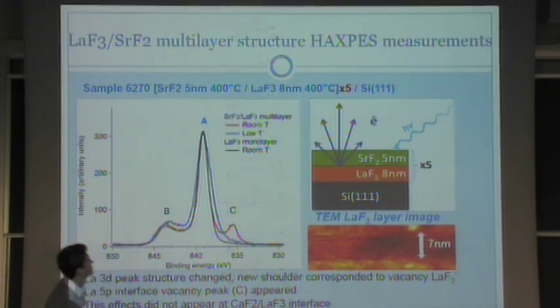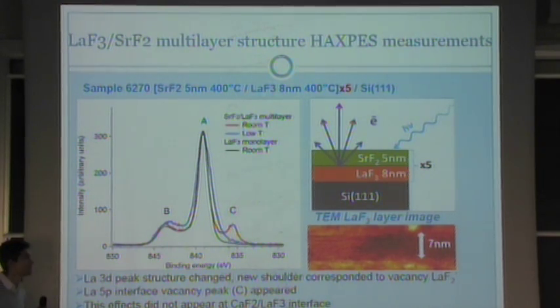Now I want to say a few words about the most interesting part of my work, which is multilayers. The multilayers were studied with the following geometry: lanthanum fluoride was under strontium fluoride, and this was repeated 5 times, so it's 10 layers of different material. Here is presented the signal from the buried lanthanum fluoride layer, and as you can see, a new feature C appeared from the beginning.